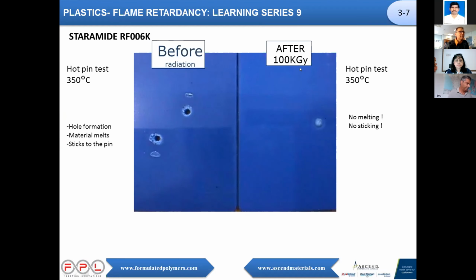And you see the same plate after cross-linking, you see that you just have a small print of a specimen, meaning that the material could withstand 100 kGy of radiation and still pass the hot pin test at 350 degrees C for a certain period of time without melting. So this is why we say we are converting thermoplastics into a thermoset, because the material is not melting anymore and it's not sticking anymore. And sticking is so important for people in electrical application. Because when you test, for example, a contactor, most of the time the contactor fails because at a certain period of time, the contact gets so hot that it sticks to the plastics. And then end of the story. With this material, you have no sticking, you have no deformation, so your material can last much, much longer.